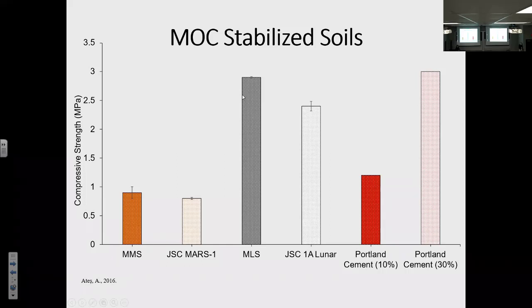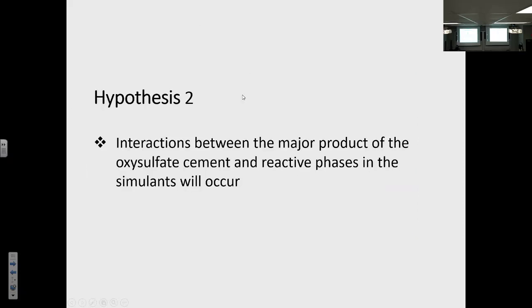Whereas for the lunar samples, we saw some pretty incredible increase in strength. So these compare better to the 30% Portland cement stabilized soils. And we wanted to investigate further why it was so. So with our SEM images, we come to that conclusion. Our second hypothesis was that interactions between the major products of the magnesium oxysulfate cement and the reactive phases in the simulants will occur.